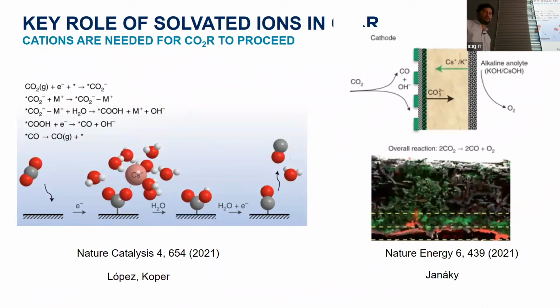The importance of cations is something that we, the community, still have a lot to learn from. There are several recent works. One from Nuria with copper, where they show that potassium, or in general the cations, are crucial to enable CO2 electro reduction. They are the ultimate responsible for activating CO2 molecules. In the absence of these metallic cations, nothing happens. And also a recent paper from the group of Janaki, where they provided the cations from the anodic side. So instead of putting these metallic salts in the cathode, they just mix them in the anode, and it was found that these salts cross over the membrane and still do some magic tricks in the cathode to enable efficient CO2 electro reduction.